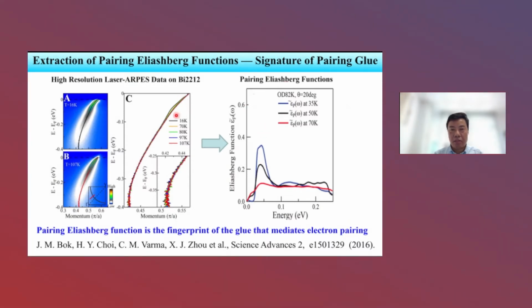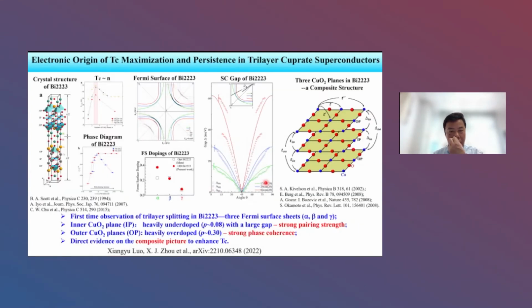But in high-Tc cuprate superconductors, because it has an anisotropic gap and an anisotropic electronic structure, I think we have to use ARPES to extract the pairing function. And I think this is the first time we can extract the pairing function in the cuprate superconductors, and it has a structure with a peak around 50 millivolts, and a very flat, high-energy feature here.